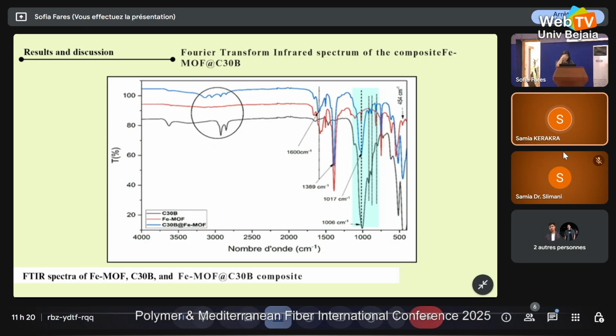And bands at 1369 and 1017 confirm the preservation of carboxylate groups in the composites, via changes in intensity showing interaction with the clay. These results confirm the successful synthesis of our composites because both clay and the MOF preserve their structure.